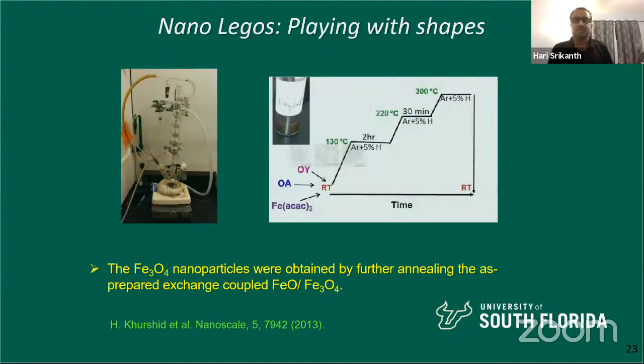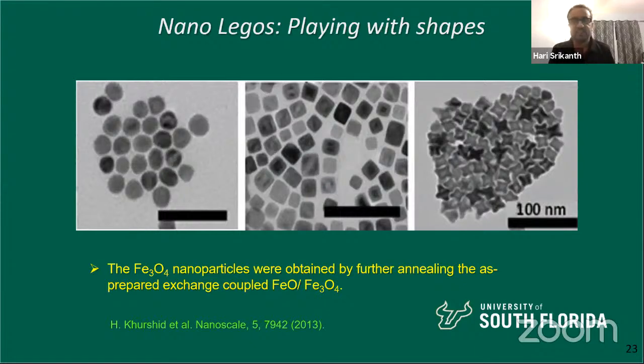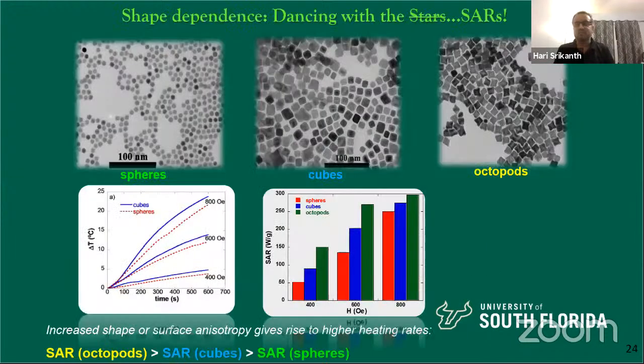So let's look at the other thing. Hafsa came to me and she said, but do you want me to play with the shapes also? And I said, sure. I mean, it's already very complicated with core shell, but she was able to play with the shapes inside. You can see the core shell, core and shell, but she was also able to change the surface anisotropy: spherical, cubic, and these star-shaped particles for the same system, okay? So that we can compare the effect of the shape anisotropy or the surface anisotropy. This is one of the most important slides in this presentation. Here's the comparison: spheres, cubes, octopods, or these exotic shapes. Just look at this right here.